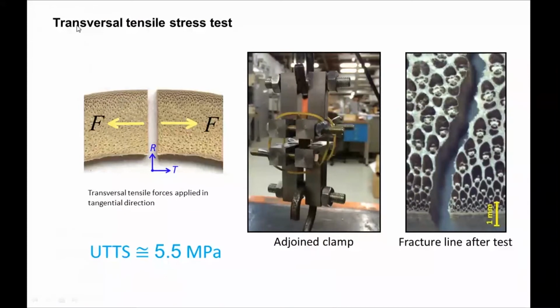In the transversal tensile stress test, you can see the ultimate transversal tensile strength is about 5.5 megapascal, and as you can see, the fracture line passes through only the parenchyma, not the sclerenchyma or the fibers, only the parenchyma. In this way you can measure the tensile resistance of the matrix.